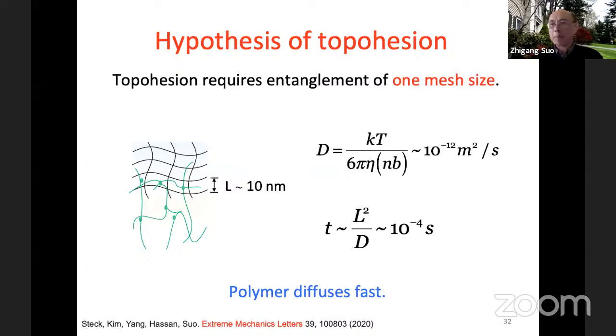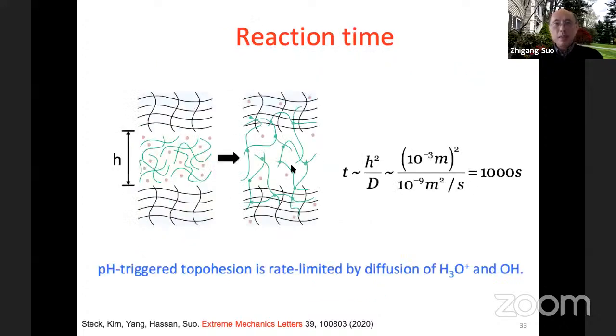Diffusion is not the problem—it's the reaction that's the problem. It's a surprise to us; we did not anticipate this before. So then we ask, what is your reaction time? It's interesting in our case, in our pH-triggered topohesion. For pH-triggered topohesion, you need diffusion of hydrogen ions or OH ions. So you need to diffuse these ions, and this diffusion needs to occur across the thickness of your material.